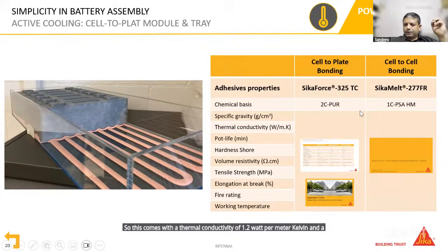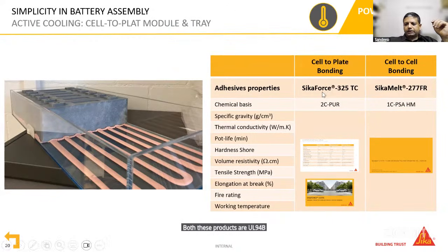So this comes with a thermal conductivity of 1.2 watt per meter Kelvin and a strength of almost 11 MPa. And the second product, what you see over here, Sika Melt, is basically for the cell-to-cell bonding. So in the case of a prismatic cell, Sika Melt can be used, and this is also a removable product. It is more like a pressure-sensitive adhesive that can be applied between the cells to keep them mechanically bonded. Both these products are UL94 V0 rated, and 325 TC, like I mentioned earlier, is a non-removable bond. So the only way you can remove the cells is by destructive methods.